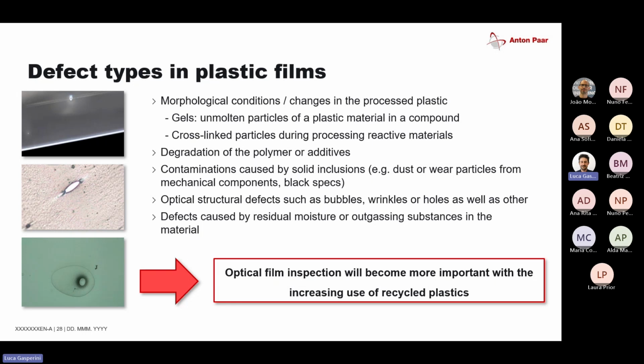It could be when there is locally a different molecular weight somewhere, which can happen, especially during recycling, or if there are cross-linked particles, which form during the processing of reactive materials. If there are some spots with degraded material, they can appear as black spots, or additives that are somehow not really molten inside of the foil. If you have any contaminations like dust, sand, or abrasions from mechanical parts, you often see them also as black spots. And of course, holes will also be detected by the FQA.